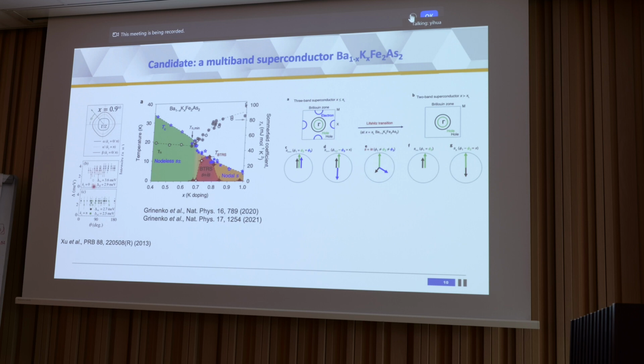Professor Hong Ding's group showed very early on through the ARPES measurement that this material has more than one band crossing the Fermi level, and the superconducting gaps are quite different for at least two of them. Grinenko has shown in this very nice work that this material breaks time reversal symmetry when the doping of the potassium is between 0.7 and 0.85. He showed further that if the doping level is at 0.77, the so-called magic doping, the phase factors between these different components are locked from each other, and the phase angles are neither 0 nor pi, so that it breaks time reversal symmetry this way.